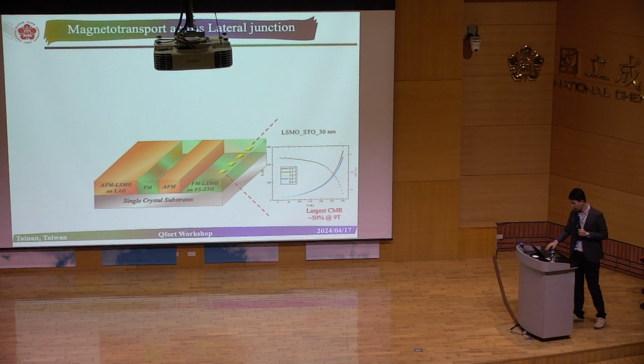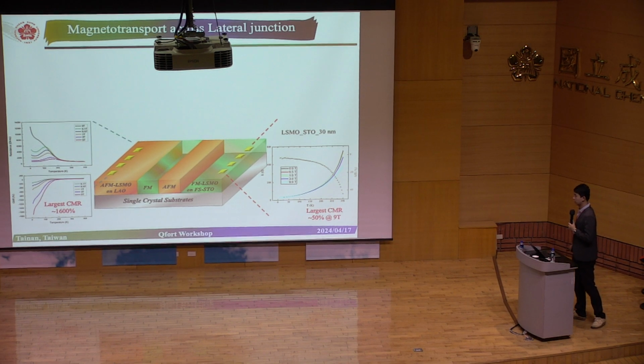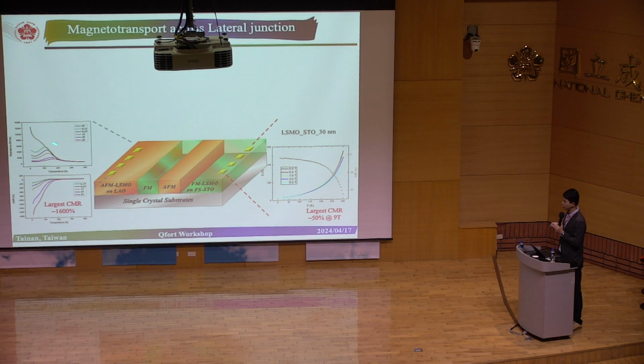All right, if you look at the left side, we do the magnetic transport on the anti-ferromagnetic LSMO. Originally it's insulating, which is a classic feature for anti-ferromagnetic species. But once you apply a large enough magnetic field, you can suppress the interactions in the material, and so you can induce the phase transition once again.